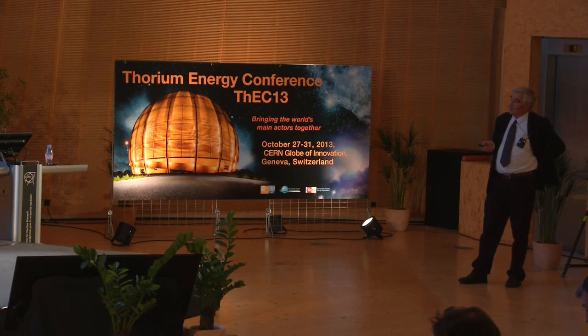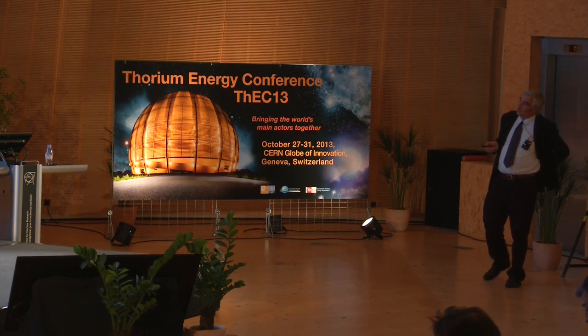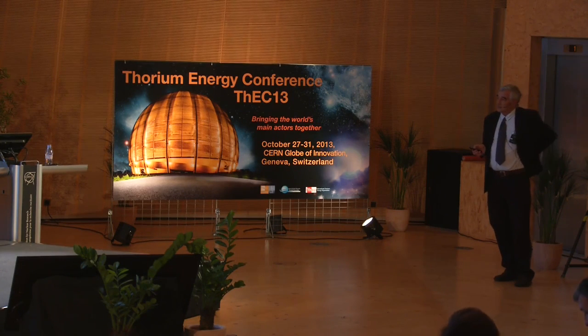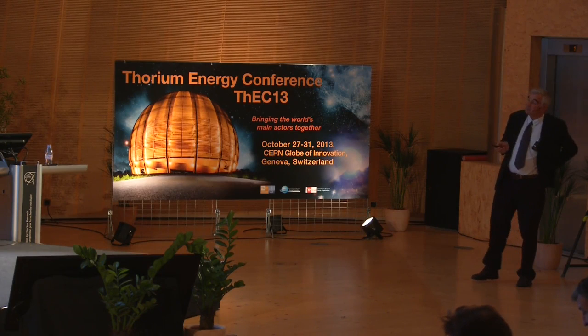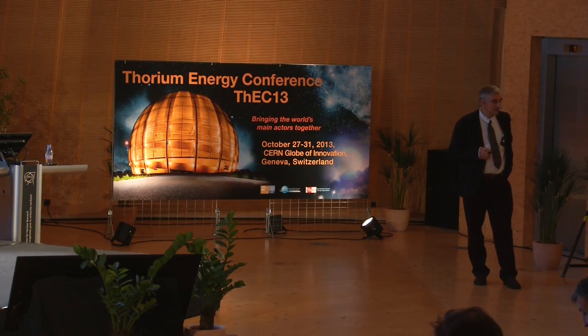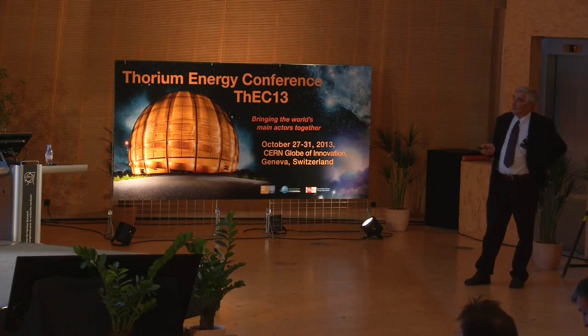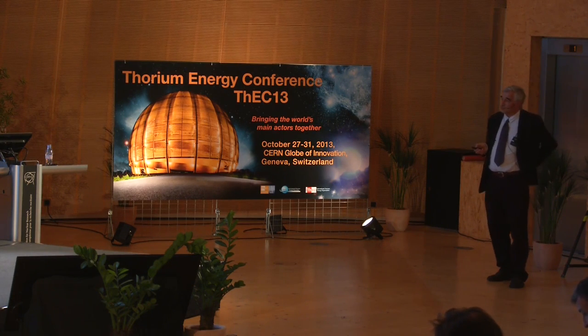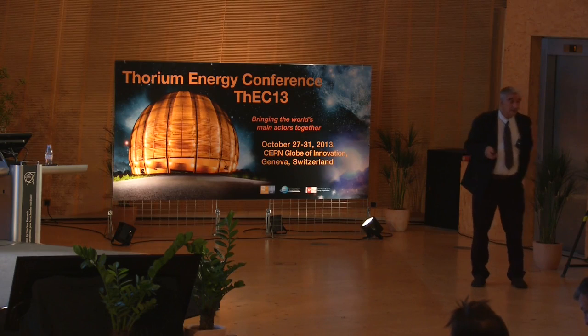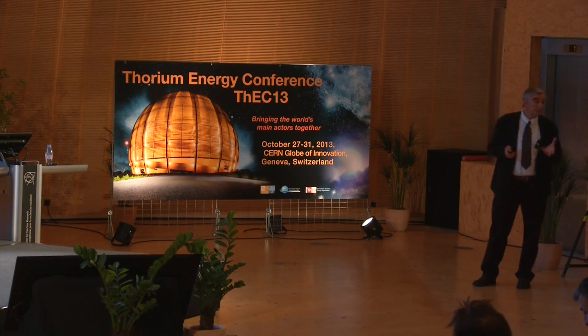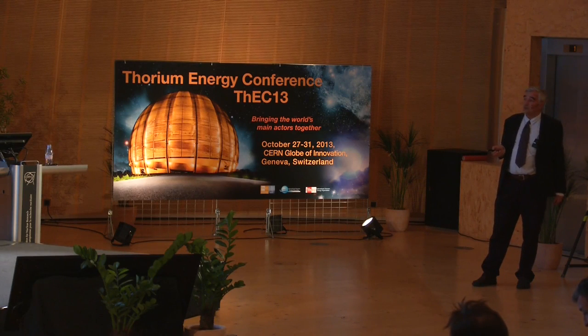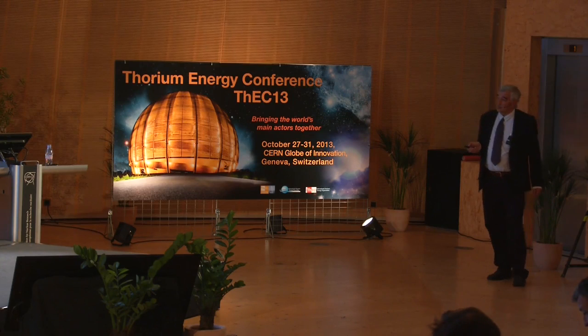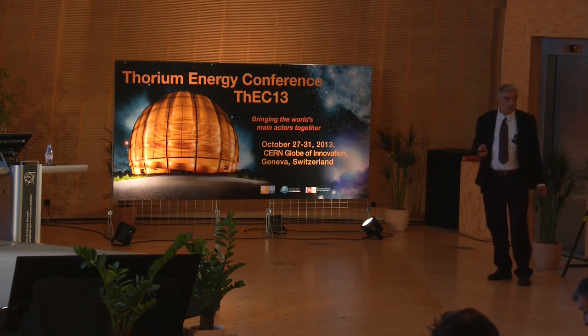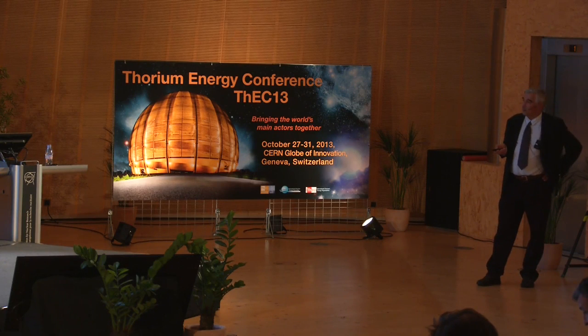I won't go into much detail. What we have observed, nevertheless, in the bottom of the safe hull is that there was some leak. We estimate that maybe there was some leak of oil, which produced a little amount of carbon products in the bottom. There was also an in-service inspection of this target in order to check if the thickness had been modified by the operation. And what we have seen is that there was no detectable change in the thickness of the window. So the technique was very efficient in order to check the thickness of the window.